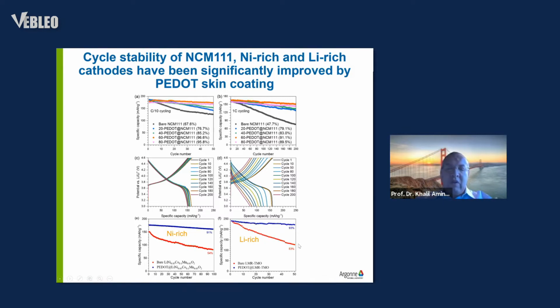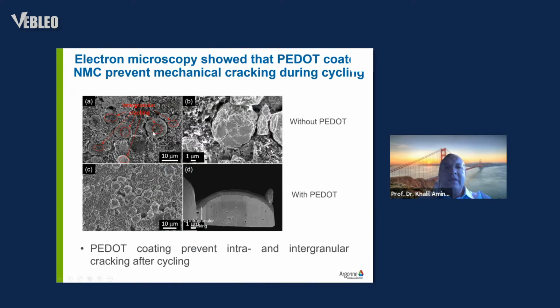So again, as I said, the biggest concern is cracking and oxygen release because it can affect the safety of the cell. So we looked at that as well. Here is a material that has been cycled for 100 cycles at 4.6 volt. As you can see, there is tremendous cracking when you don't have protection. Once you get the PEDOT coating protection, we don't see any cracking at all, which means we don't have any phase transition from layered to spinel that caused the strain that created this cracking.